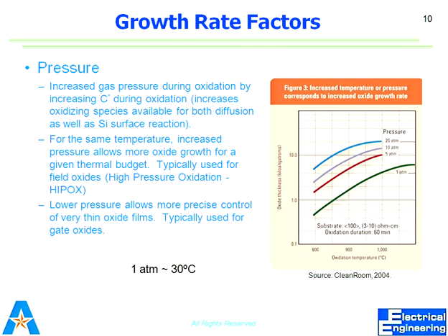Typically when you need a thick oxide layer, you go for high pressure oxidation. In the case of high pressure you get the thicker layer in less time, meaning you have a high reaction rate and high growth rate, but the quality would not be that good. So it's always a trade-off.